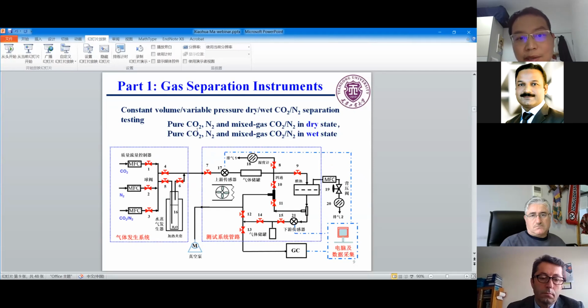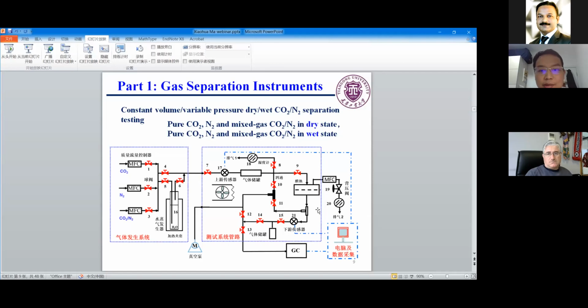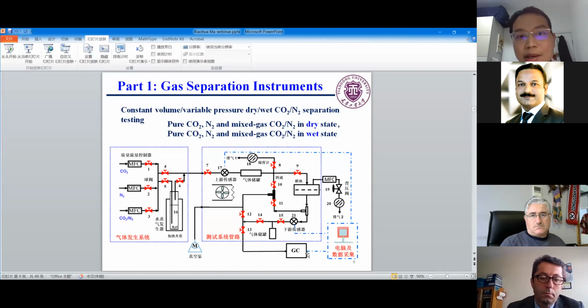By controlling the wet and the dry gas, we can send this gas to the upstream, and then we can use the transducer to check the accumulated gas in the downstream, and also use the GC to get the component of each gas. In this case, you can get the permeability of the membrane for CO2 and nitrogen at dry state, the mixed gas of CO2 and nitrogen at dry state, and also the pure CO2 and nitrogen, and also the mixed CO2 and nitrogen at humidity states.